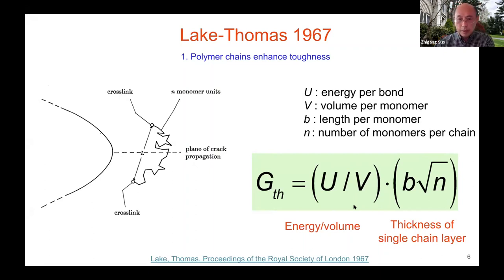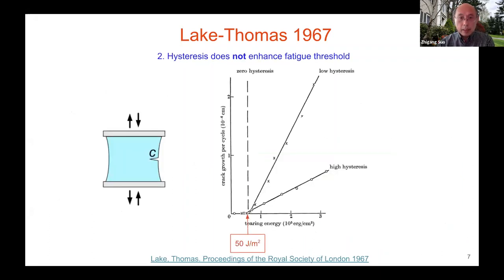So now, let's go on. Now this is insight one. Insight number two, so let me summarize this: hysteresis does not enhance fatigue threshold. Fatigue is the following. You still have the crack, same sample, but you do cyclic loading. What you measure is a crack extension per cycle. So this is a crack growth per cycle as a function of applied load. Here is this energy per unit area.